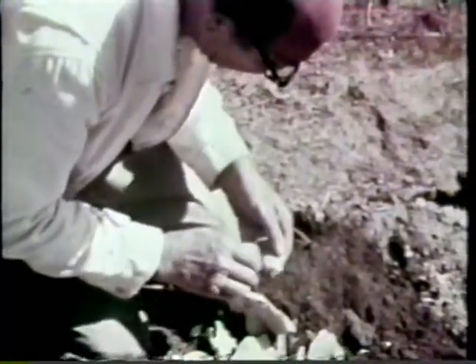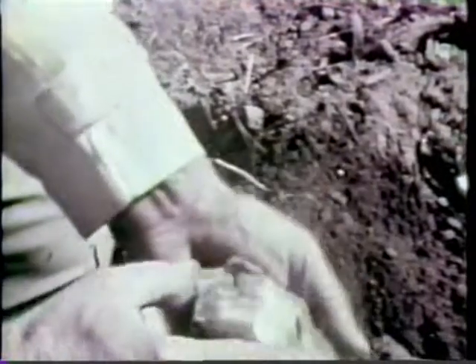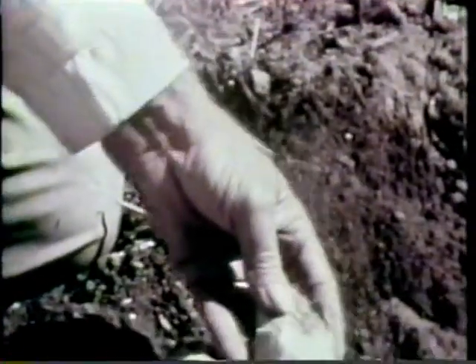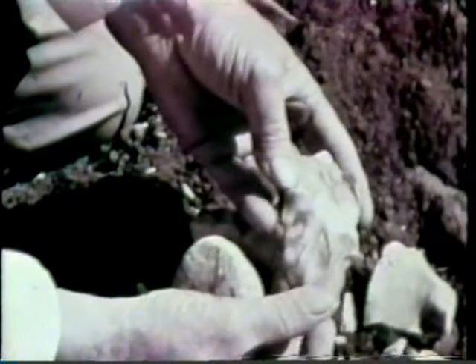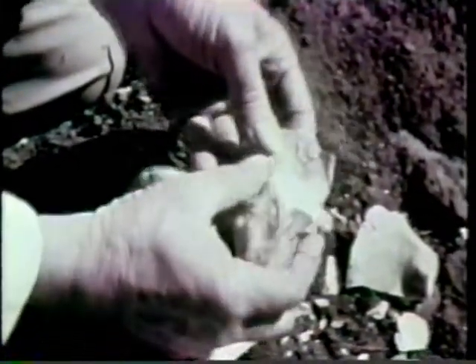To measure the effect of the heat treatment, flakes are struck from cores and put in the oven. Highly siliceous rocks, in their natural state, are granular. By heat treating, the material may be altered to make it more glassy and easier to work. It will respond better to both percussion and pressure. Flaws are eased and internal strains are relieved. Flakes are much sharper because of the reduction of crystal size.